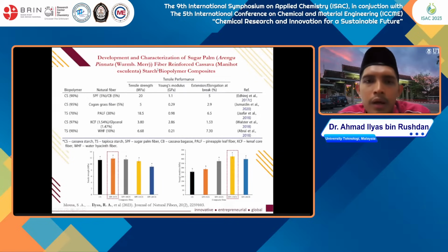These are some of the experiments we have done, published in the Journal of Natural Fiber, a Q1 journal. We can see that the tensile strength and mechanical properties were increasing after we added several loadings of the fiber. However, at some point it decreases due to the agglomeration of fiber, which does not give a better interfacial bond between the starch and fiber.